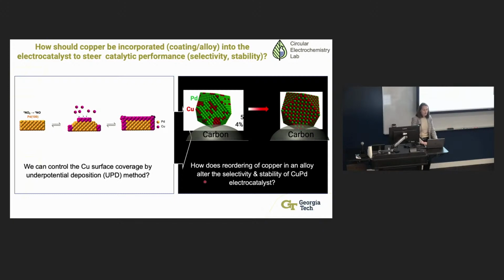And then the second approach that we looked at is to just try to make alloys where the copper was interdispersed in the metallic catalyst. A very simple way to do that. We can do this in the wet lab with traditional manufacturing methods. But a lot of times you get these randomly ordered catalysts. And the challenge with that is that throughout your catalysis, the atoms are going to be constantly migrating in the metal, and so you may have changes in product selectivity. As we saw, very slight changes in a surface facet change catalysis. And so if they're not stable, you could also see changes in catalysis.